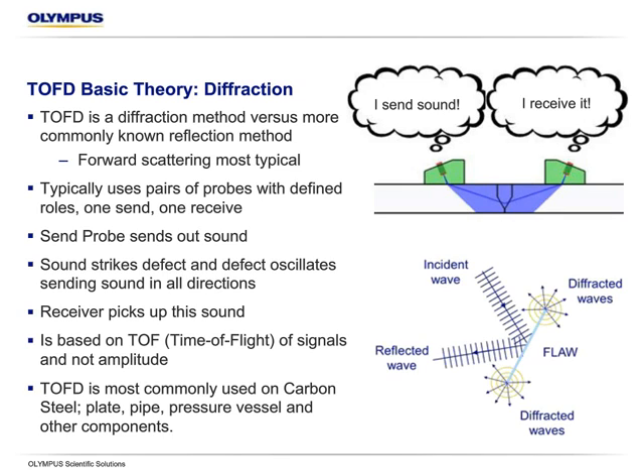Normally we use a pair of probes. If we're doing weld inspection, that's one on each side. There are instances we'll see later where we might do a variation of that, but typically we have one probe that's sending the sound, the other is set up as the receiver on the instrument, and that's really the sound that we're getting back and the sound we're interested in.